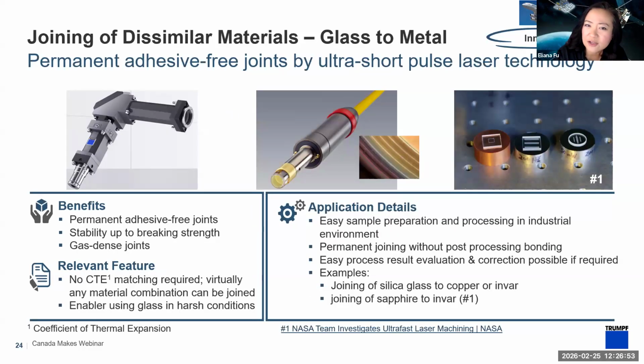Another one to do adhesive-free joints would be using ultra-short pulse lasers. So again, you're not introducing a chemical into the process of joining, so no gluing is required, and you can create a gas-tight joint. So you don't have to worry about the mismatch in thermal expansion coefficient. Virtually any material combination can be used. And this is especially great for things like glass. So trying to join these kind of dissimilar materials together. So an example of this would be joining silica glass to metal like copper Invar, or joining sapphire glass to Invar as well, which is what we've shown in this image here. And this process has even been qualified by NASA, so that's pretty cool.